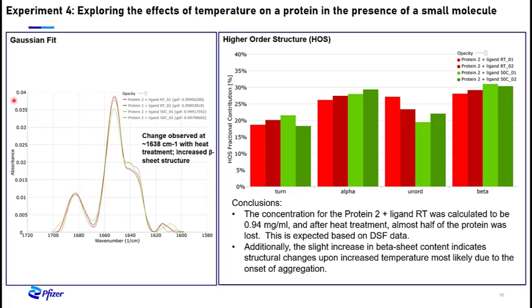In our final slide from experiment 4, you can see on the left the Gaussian fit curve. This plot is showing the goodness of fit, and here you can see the obvious change in beta structure upon heat treatment. To the right is our higher order structure bar graph, which is generated from the Gaussian curve. This also shows an increase in beta sheet content, although nothing dramatic, because remember here we do have a ligand bound to this protein.